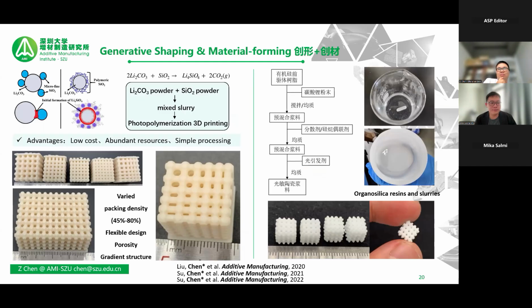The second thing is that we propose a generative shaping and material forming strategy, in Chinese 创形创材, because the lithium orthosilicate material itself is very expensive. We can say it's not commercially available, because we have to get the powder from our collaborator. There's no existence in the commercial market. So it is expensive, that's the first thing, and secondly, it's sensitive to air. These two issues are not easy to tackle. So we try a combination of A plus B, meaning two inorganic materials. This one and silicon dioxide, these two materials